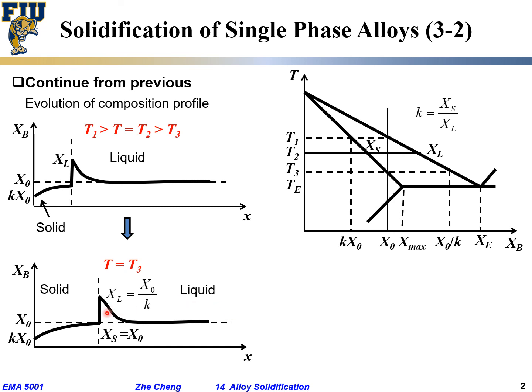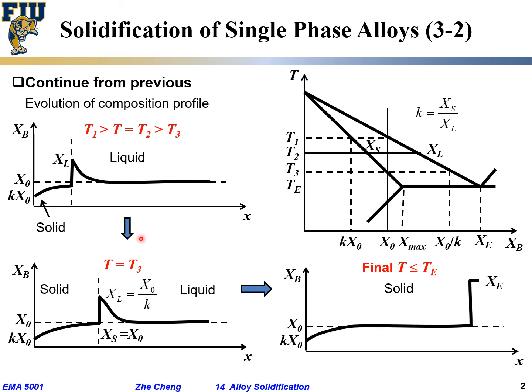In order for this local region to go from liquid to solid, the local solute has to be diffused deeper into the liquid, and that quite often limits how fast the solidification can happen. That's how the steady state rate will be determined by how fast I can reject — diffuse — the solute from the local peak into deeper into the liquid, so that I can go from liquid here into solid here. Eventually, we are very close to the eutectic temperature. My solid would have a large composition which is relatively flat at x0. Then within the eutectic I have a change in eutectic composition. That's what it's going to look like within this material, if it's controlled by a diffusion process.